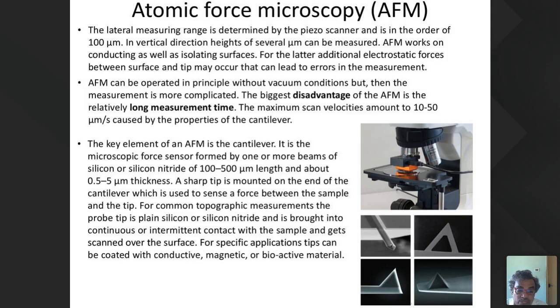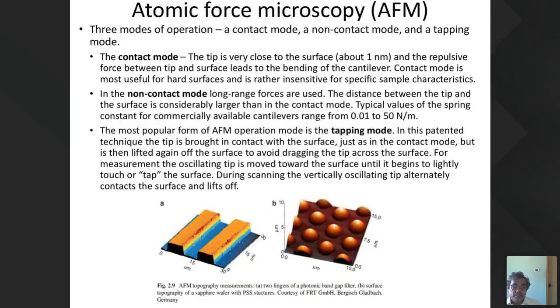It is a microscopic force sensor formed by one or more beams of silicon or silicon nitride of 100 to 500 micron length and about 0.5 to 5 micron thickness. A sharp tip is mounted on the end of the cantilever, which is used to sense the force between the sample and the tip. Okay. For common topographic measurement, the probe tip is plain silicon or silicon nitride. Okay. For specific applications, tips can be coated with a conductive, magnetic or bioactive material.